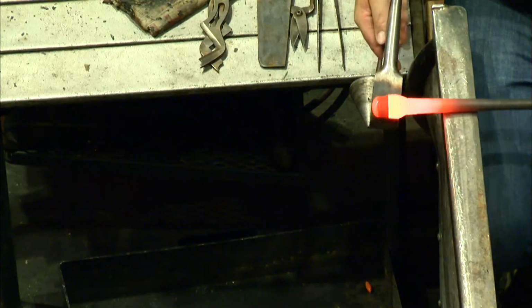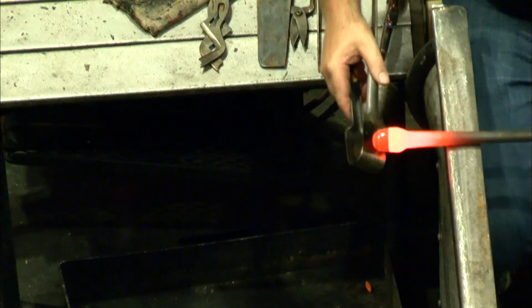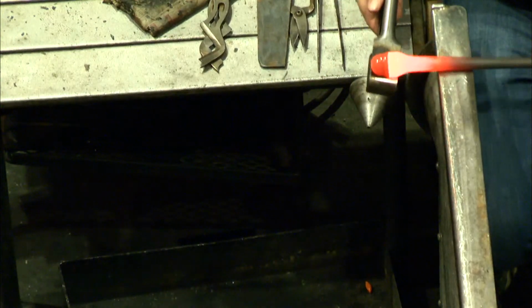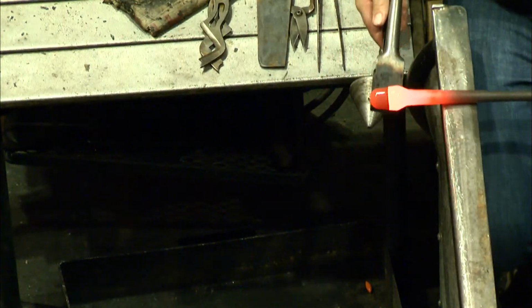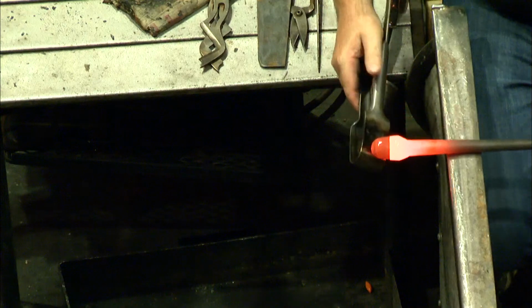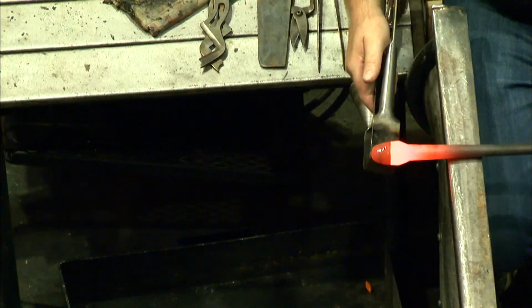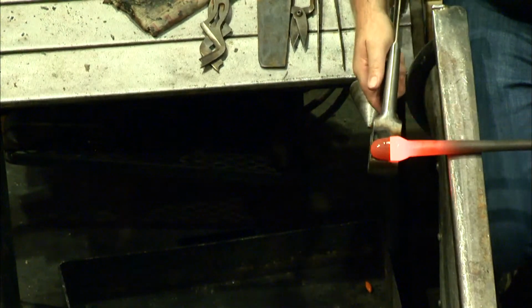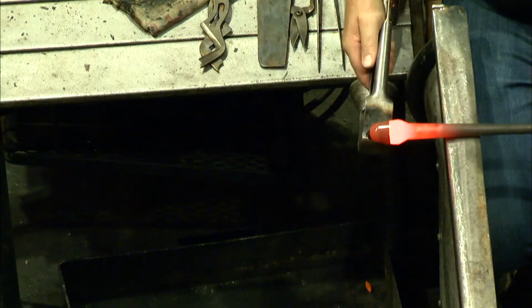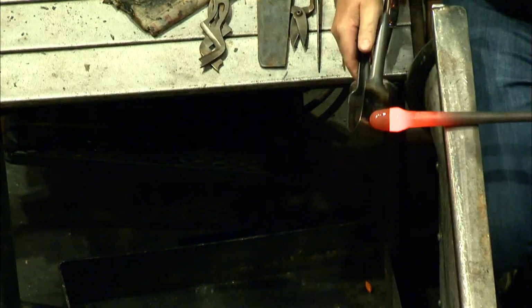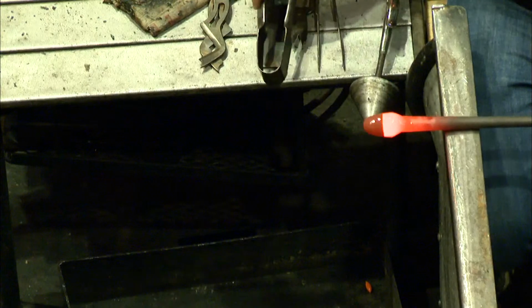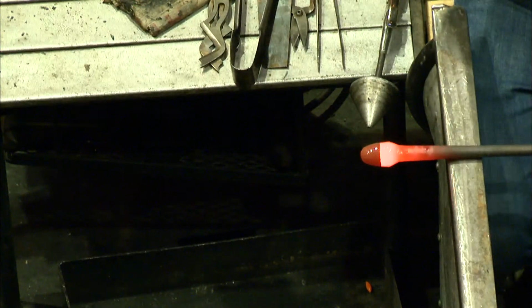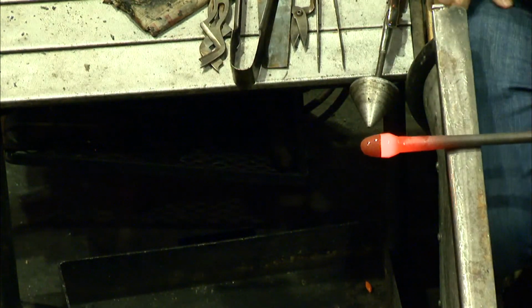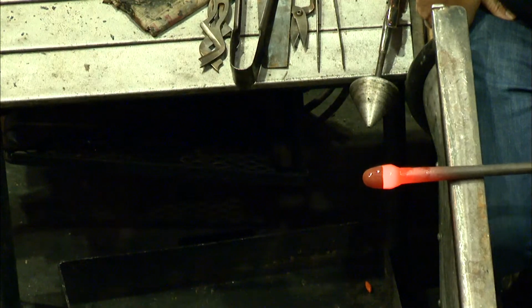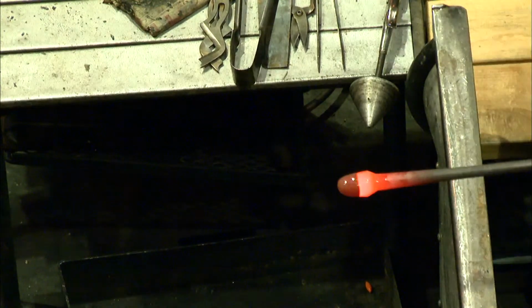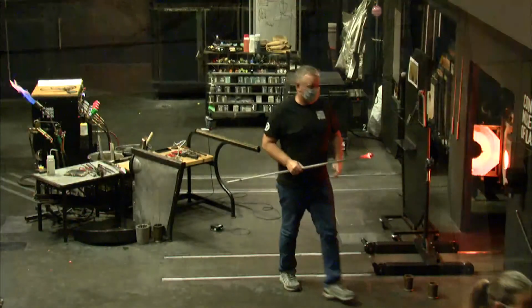So now these two have traded pipes. George is going to be getting that colored glass into a nice, agreeable shape to be able to collect more clear glass over the top of it. And what I mean by that is he essentially is shaping it into like a Q-tip shape. And what this does is allows him to plunge that glass below the surface of our molten glass that we have in our melting furnace without the risk of trapping any air bubbles between those two materials.